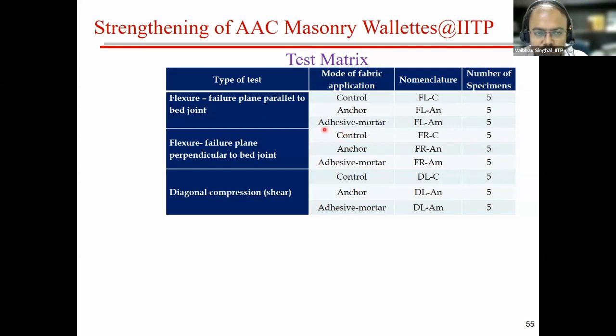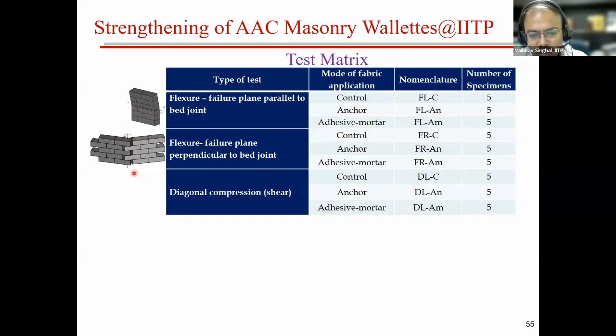So we decided to perform small, simple tests. A flexure test where the failure can be parallel to the bed joint. So you can see this is the failure mode. A flexure test where the failure can be perpendicular to the bed joint, so failure is expected something like this. And then another diagonal compression test to find out the shear or indirectly the tensile strength of a masonry.